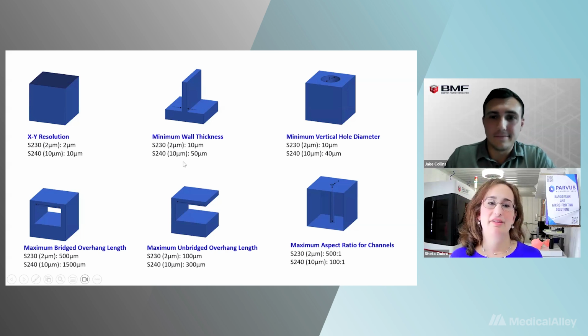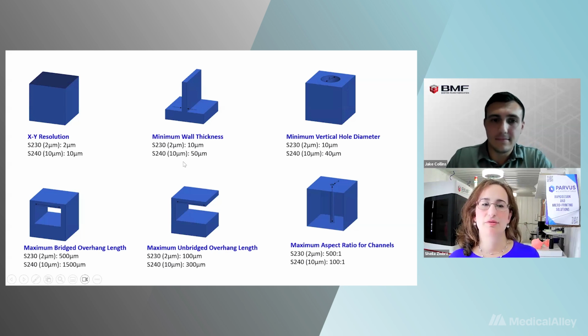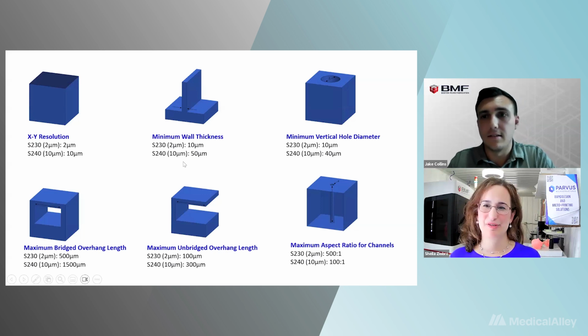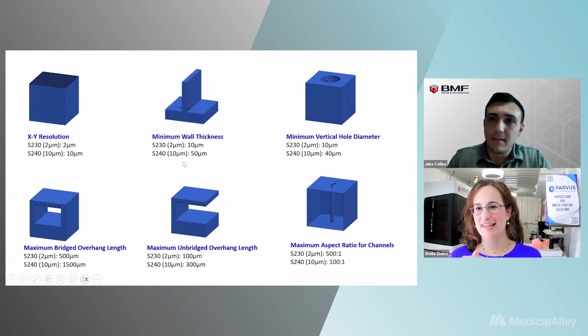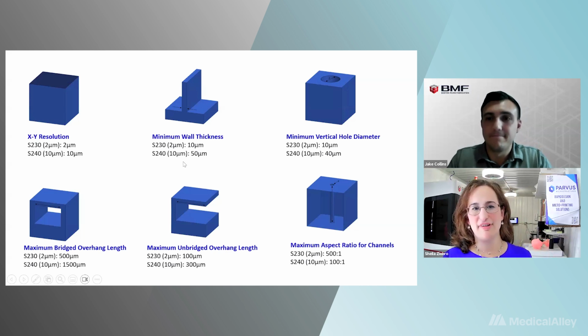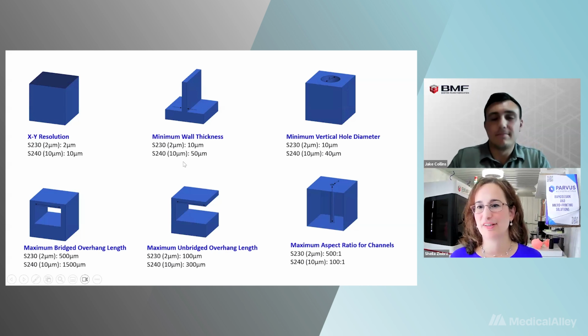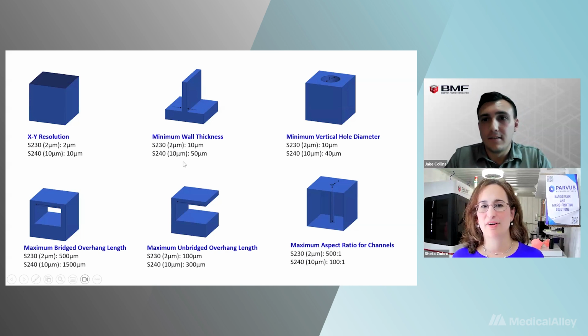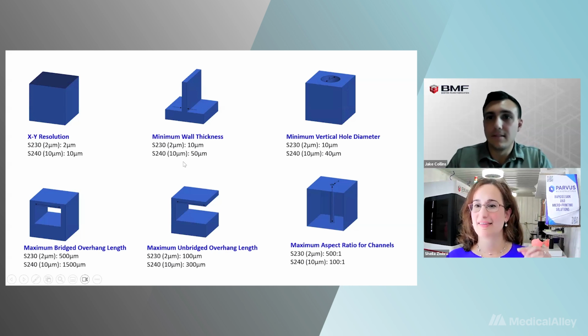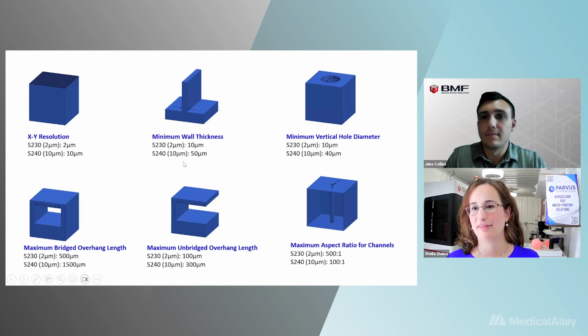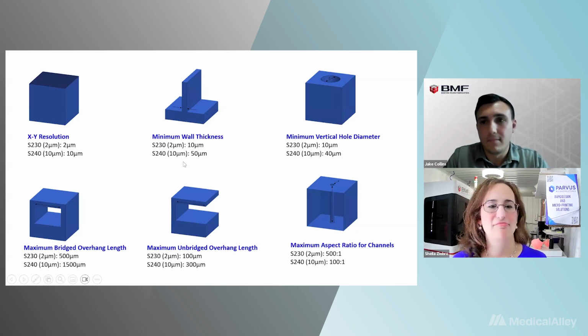Absolutely. Another point to make is that you were talking about the optical resolution, or XY, and that's different. I know a lot of times when we're talking to people, they get confused by that. The layer thickness is the Z height, and that's going to be different than the optical resolution. For the 2 micron, you can have 5, 10, even 20 micron layer heights in the Z direction. And for the 10 micron, you can have 10, 20, up to 40 micron layer heights.